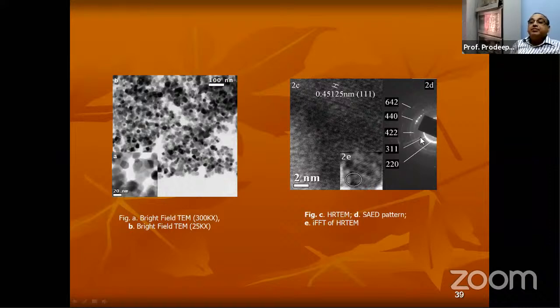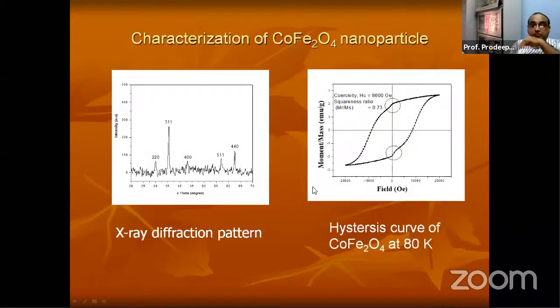And this is HRTEM. It shows fringes which confirm the structure of the cobalt ferrite. And this is the X-ray diffraction pattern. This kind of baseline shows that it is in the nano range, and it is actually crystalline in nature. And this is a hysteresis curve which shows that they were highly magnetized.